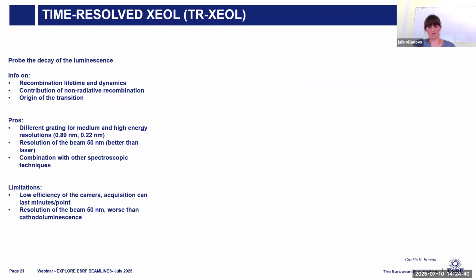With XEOL, we can collect the produced luminescence, but we can also study the decay of this luminescence, in order to have additional information: to determine, for example, the recombination lifetime and dynamics, to localize the contribution of some non-radiative recombination in the sample, and also to give more information on the origin of the transition. So this is done thanks to